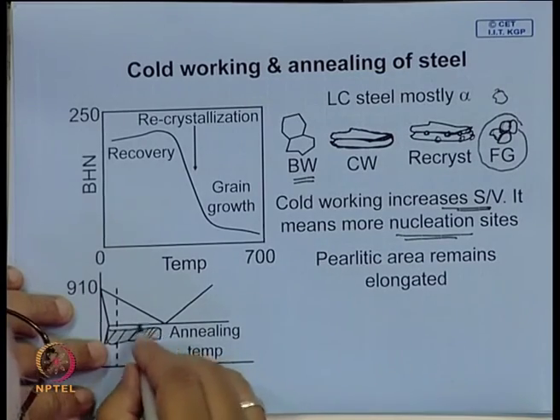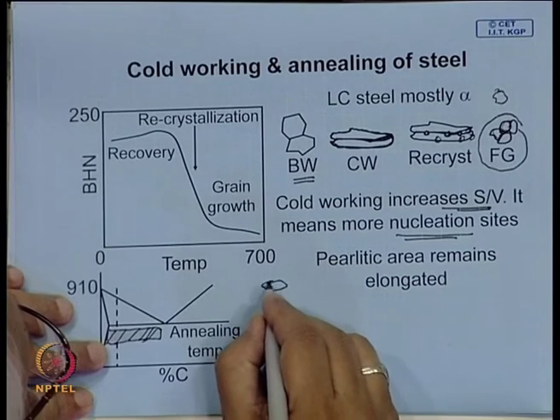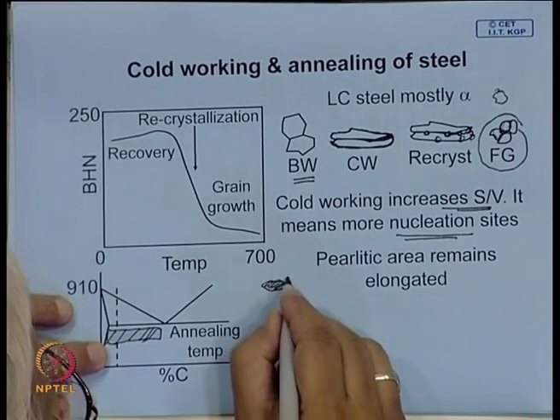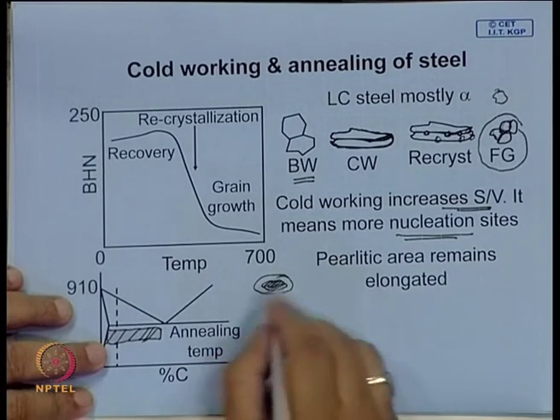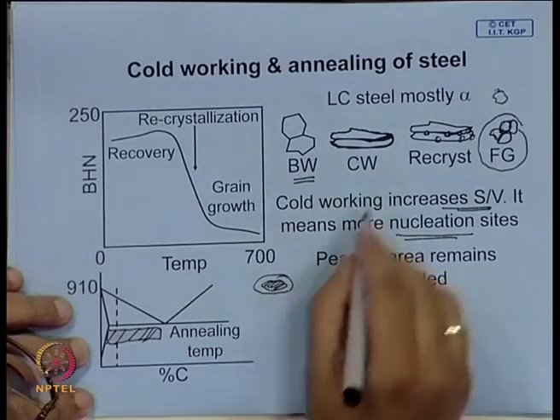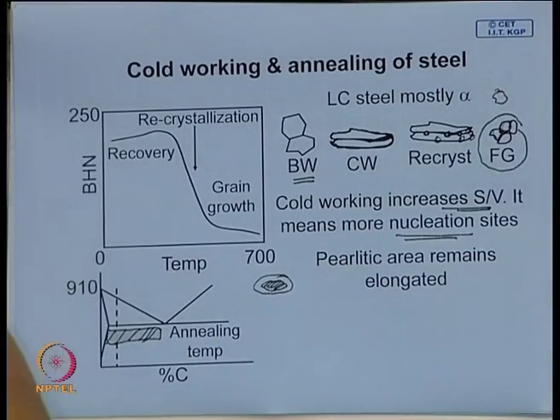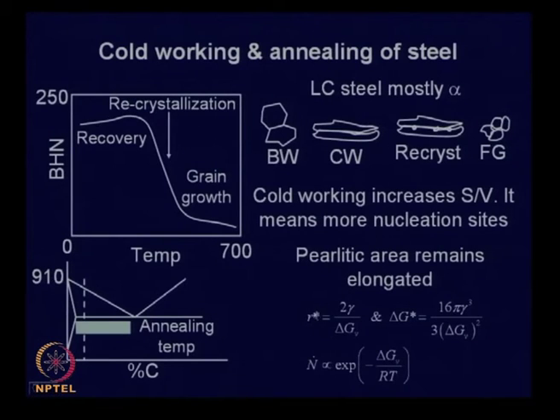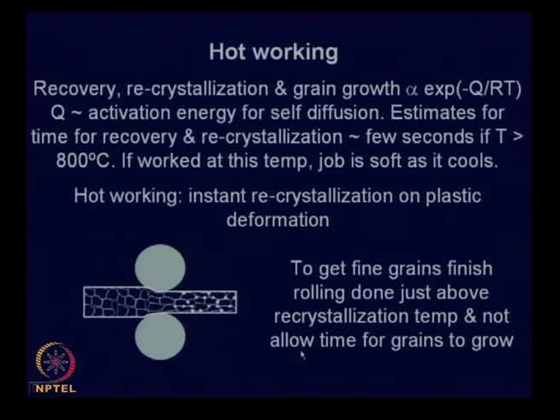So, definitely the pearlite, if at all it is there, if it gets deformed, it will remain like this. They do not undergo any recrystallization, but the ferritic region will undergo recrystallization, and you will recall that these are the critical nucleus size. So, this grain size will be determined by this critical nucleus, which is inversely proportional to the cold work. So, higher the cold work, finer will be the grain, and also higher the cold work, much lower is the activation hill which is to be overcome. So, the nucleation rate will be faster. Faster nucleation rate means finer grain.